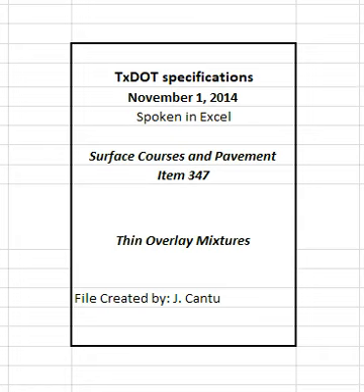4.4.2.1.13 Trial batch testing. Test the trial batch to ensure the mixture produced using the proposed JMF1 meets the mixture requirements in Table 8. Ensure the trial batch mixture is also in compliance with the Hamburg wheel test, overlay test, and drain down requirements listed in Table 7. Use a department-approved laboratory to perform the Hamburg wheel test on the trial batch mixture or request that the department perform the Hamburg wheel test.